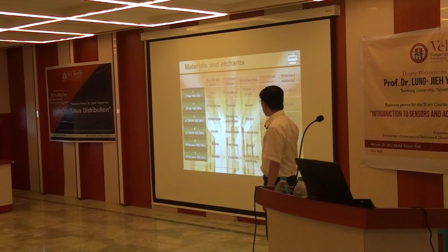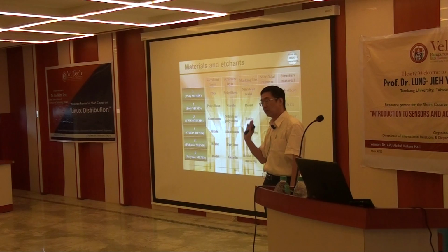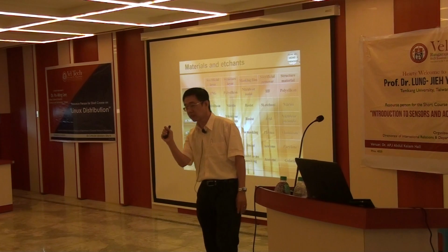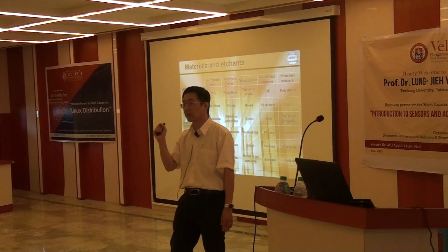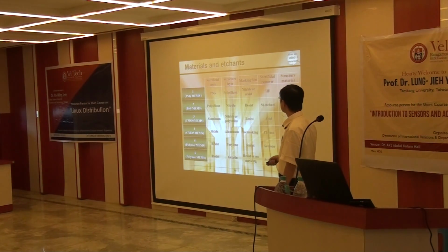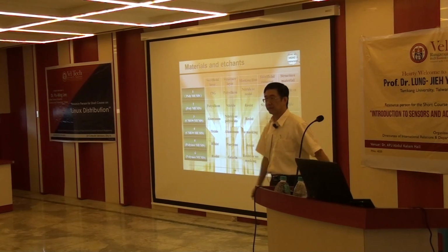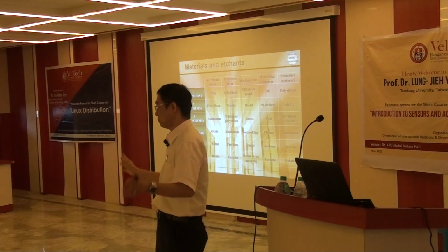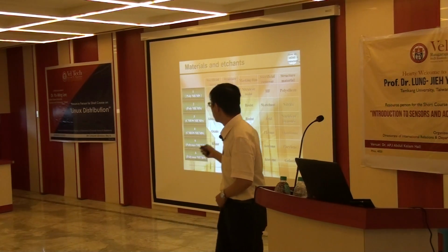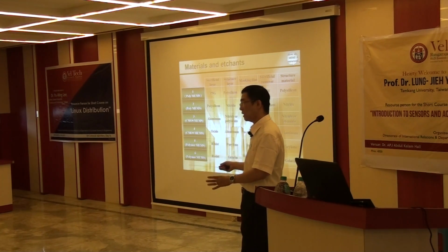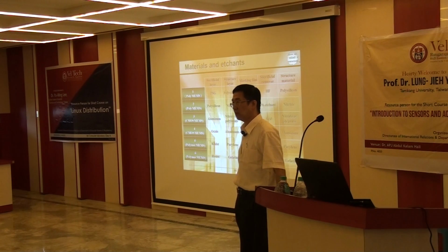Hydrofluoric acid, HF, will not attack polysilicon very much. Especially, maybe we don't use the HF, we use a very light HF, which we call BOE, buffered oxide etch. It's a low concentration HF, safe for our polysilicon. Right? So finally, your structure material, the polysilicon, stays over there. A micromotor, or even a micro tweezer, or many kinds of micro components can be done by this kind of polysilicon based process. So it's a very important process, a milestone for surface micromachining before 2000.